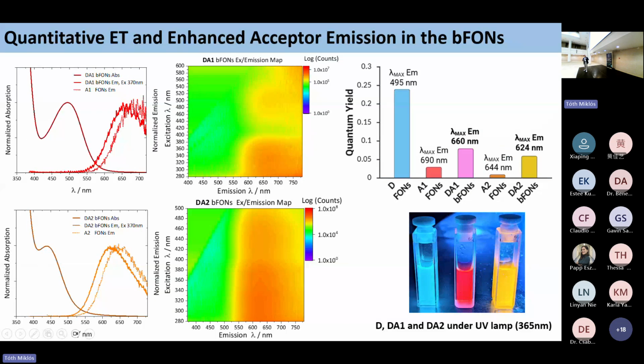Then we recorded the stationary absorption and emission spectra for the binary nanoparticles. We have seen that, interestingly, upon preferentially exciting the donor at 370 nanometers, we only see an emission signal that seems to be the one of the acceptors, with the only difference represented by a slight blue shift. And this is interesting because the energy transfer seems to be quantitative, despite the donor being both more concentrated and having a greater quantum yield with respect to the acceptors. This can also be visualized in the excitation emission maps, in which we see that no matter the excitation wavelength, only one emission signal can be collected.